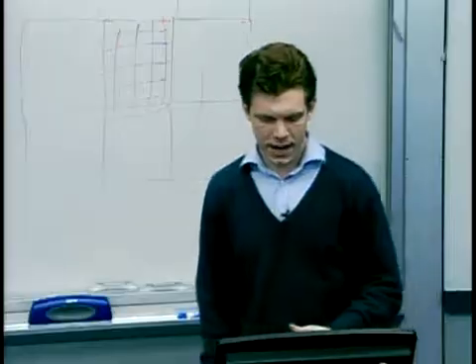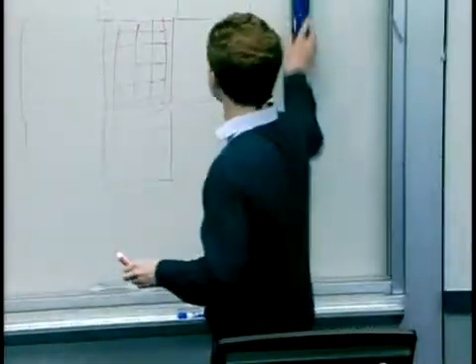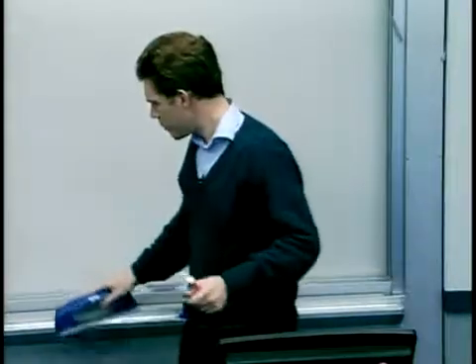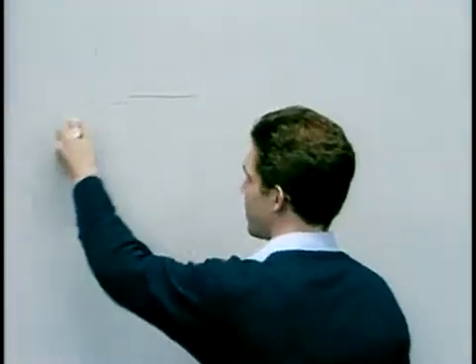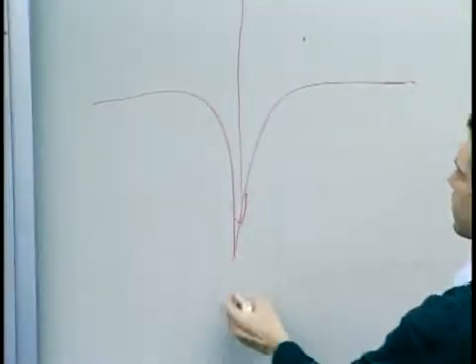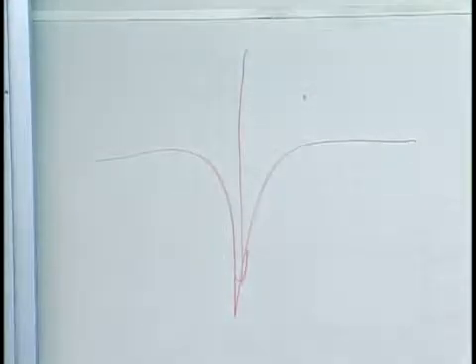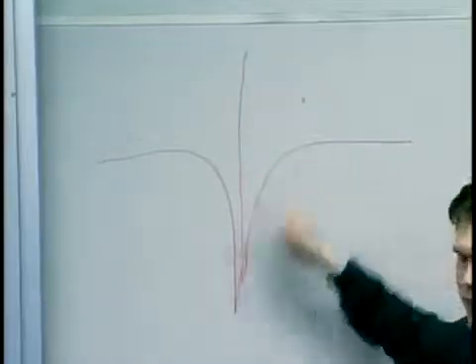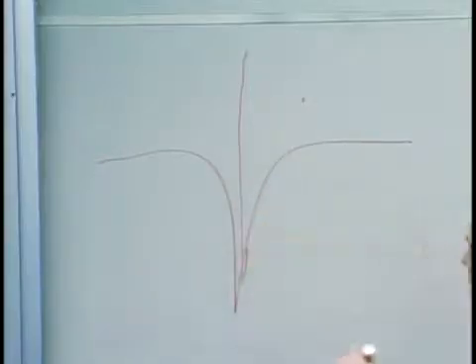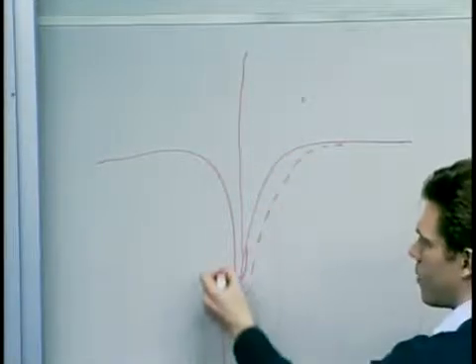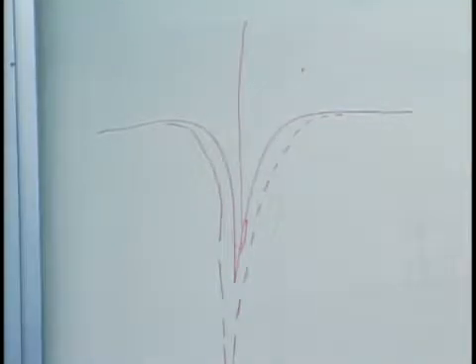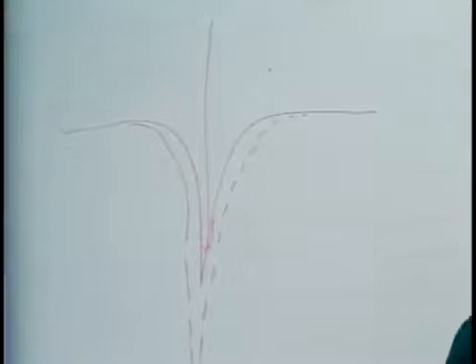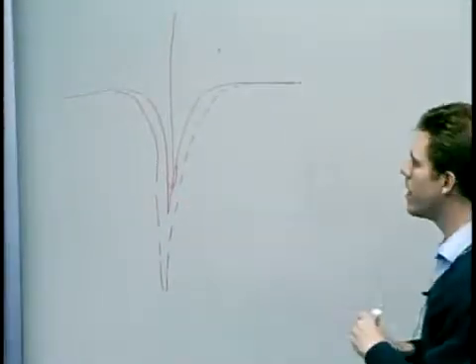So what this does in effect is takes the point load response associated with purely rubbery, purely linear elastic behavior, which would be like this, and scales it by a factor that's related to the time the load is applied. And all that's saying is, imagine this was viscoelastic. You applied a point load, you get some instantaneous deformation, but over time I'm saying this surface is just scaling down. All the points are staying in the same ratio of height, but it's just scaling down. We assumed that scale factor was proportional to the hold time, but you might not assume that.